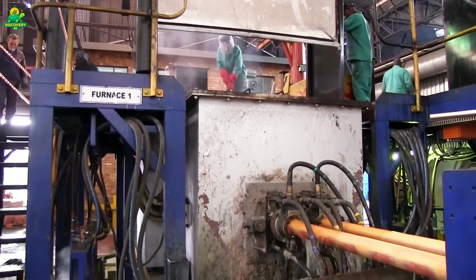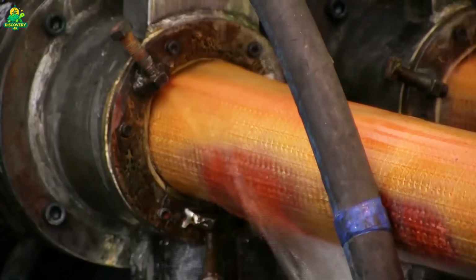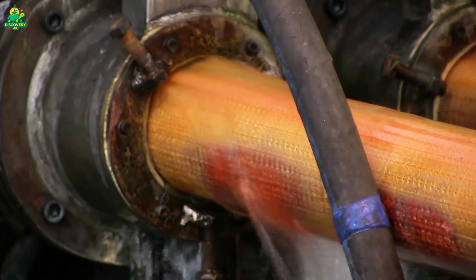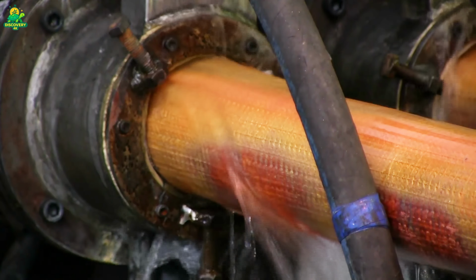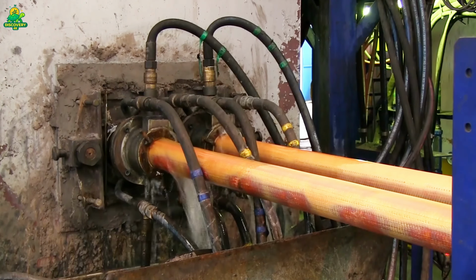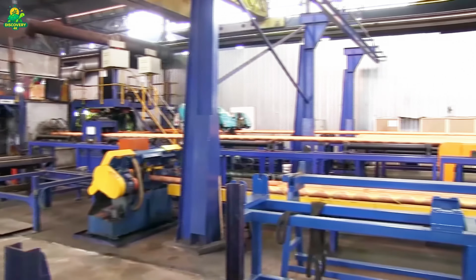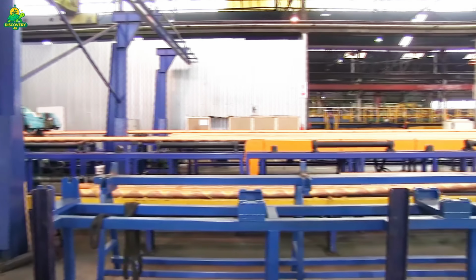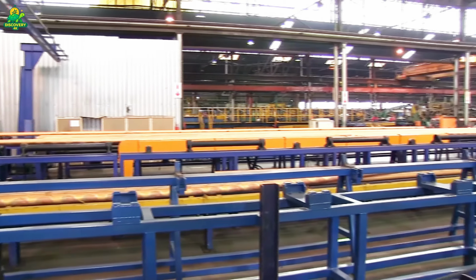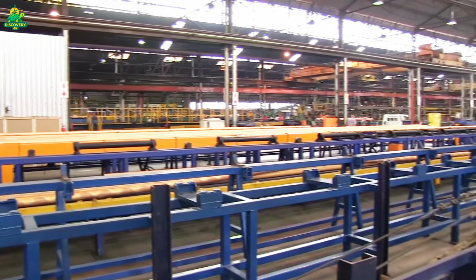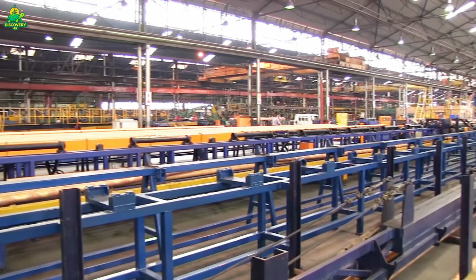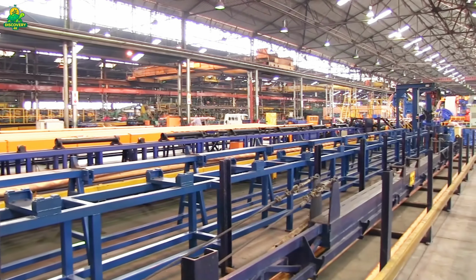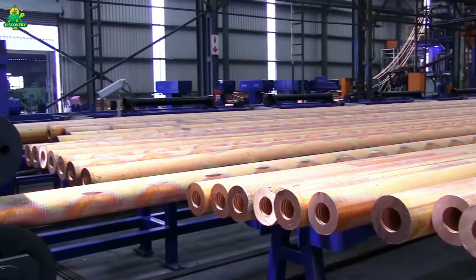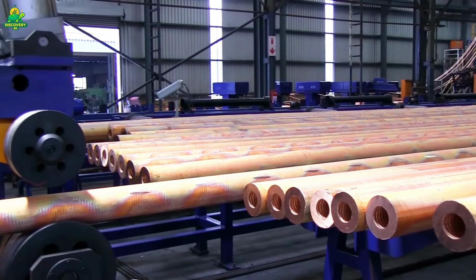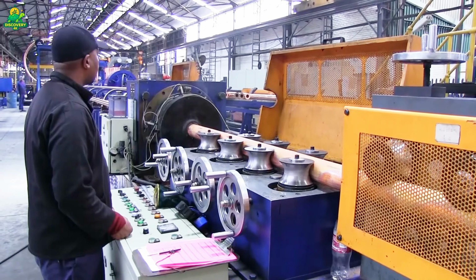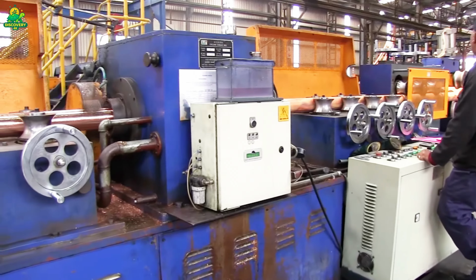The billets are reheated to around 900 degrees Celsius, soft enough to flow like clay under pressure. Then, using a hydraulic extrusion press, each billet is pushed with over 3,000 tons of force through a die, a specially shaped steel mold that creates a hollow core inside the solid billet. What emerges from the other end looks almost impossible. A perfectly continuous copper tube, glowing bright orange, sliding forward like molten silk.